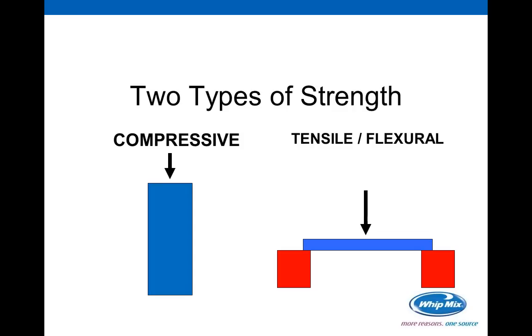The place where we get a little confused at times is when that strength issue becomes one of tensile strength or flexural strength, and that example is shown on the right-hand side of the screen where the pressure would be. This is the classic of that little lower anterior preparation that you so diligently poured into an impression, and every time you pull the model work from the impression, that little anterior prep snaps off in your stone. You get upset with a stone manufacturer, call them, and perhaps make the mistake of saying, I need to switch to a type 5 stone so that it'll be harder. It's not necessarily going to be harder, but you will remember it will be larger expansion, changing the size of everything in your end product. So you can't make that assumption.